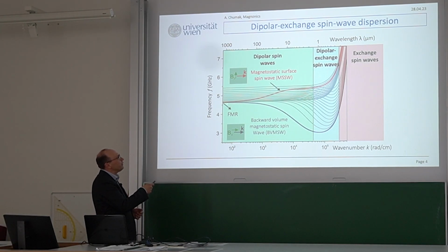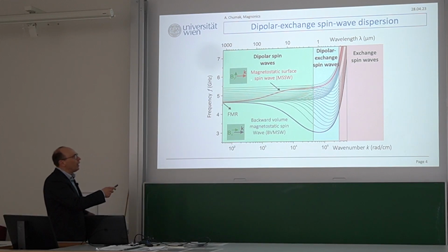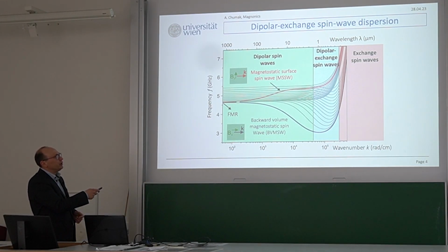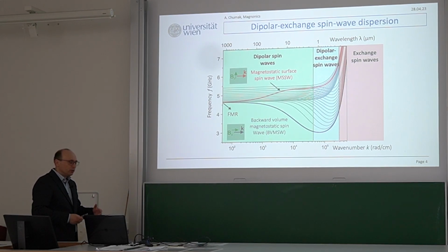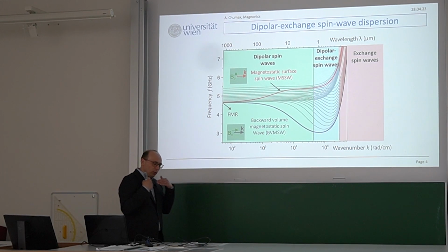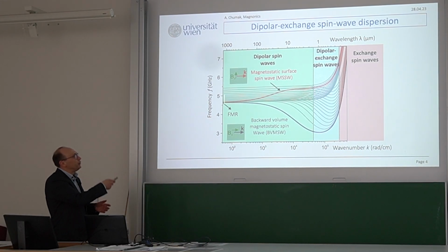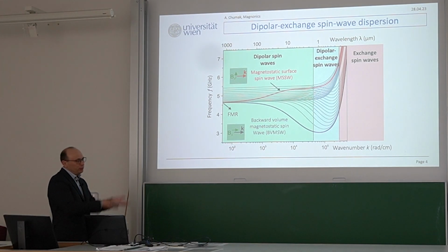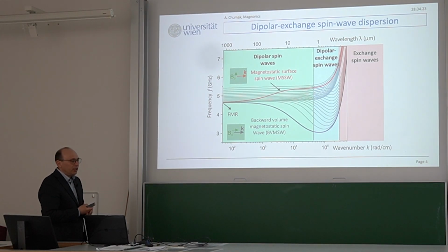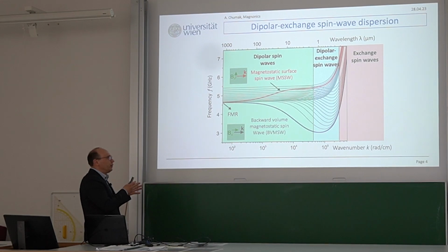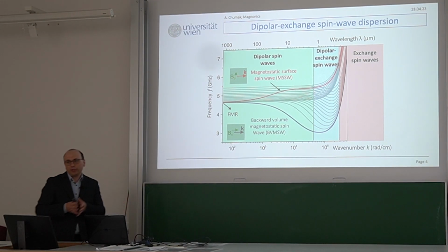If you go to this frequency or higher, and you excite something here, half the frequency will always be below the spectrum. So it means that you simply have no magnon with half the frequency where you can scatter. And in such a way, simply by tuning the frequency of the field, so usually with the field you tune the frequency, you can have a situation where 3-magnon splitting is allowed or forbidden.